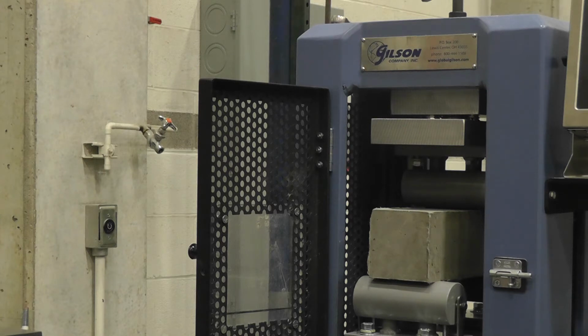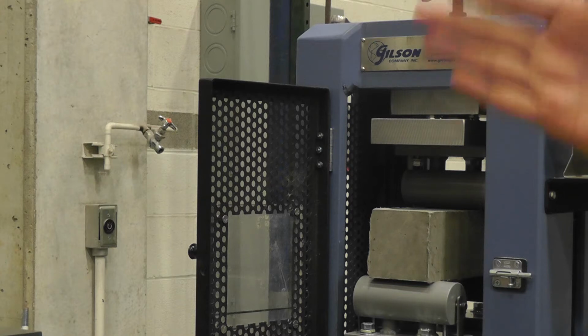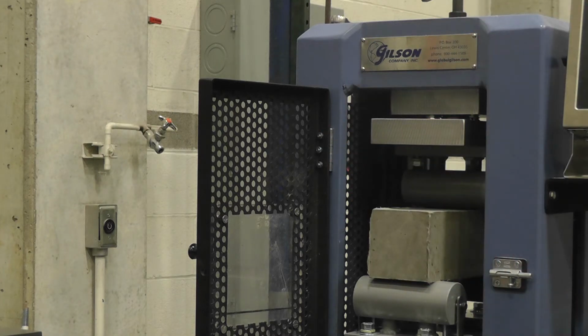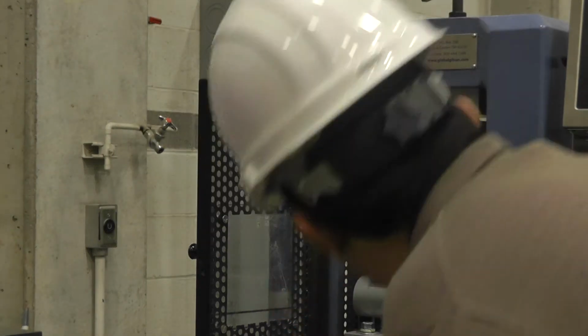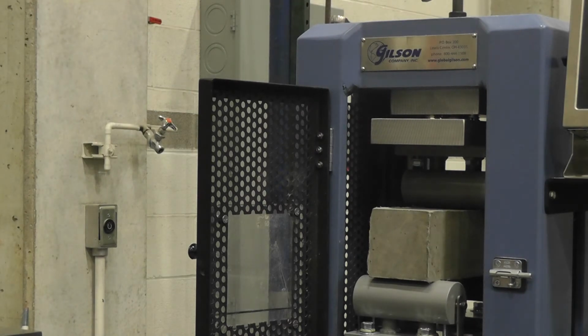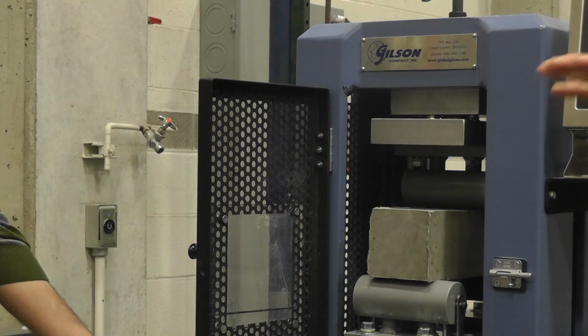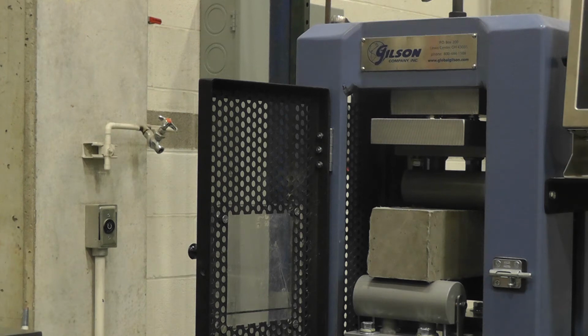So if we do the same test for a normal concrete beam, it just has one fracture, and then boom, it's done right away. So now you can see actually the load bouncing around. So what happens is it goes to a point, then it comes down a little bit because a new crack starts. Okay, and then it comes back up, comes back down, like that. So this bottom part is still going up relative to the top, so you are still bending the beam. But it's not moving as fast as before, so that elastic stage is over for the beam. It's now going into inelastic deformation.